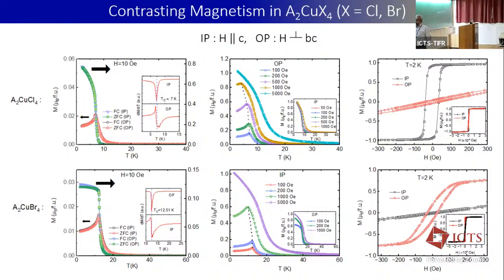But if you look at the bromine case, in the out-of-plane direction, though it shows a ferromagnetic-like behavior, look at the number: if you calculate the μB per copper, it is very small, even less than 0.15. In one case, you are getting close to 1 μB, which is expected for copper 2+. But in another case, though it looks ferromagnetic-like, the magnitude is too small. And the magnetization versus temperature is validated by this magnetization versus magnetic field. In one you see a ferromagnetic-like behavior, in another, a downfall, you see a very hard axis kind of behavior. A similar thing happens for the bromine.